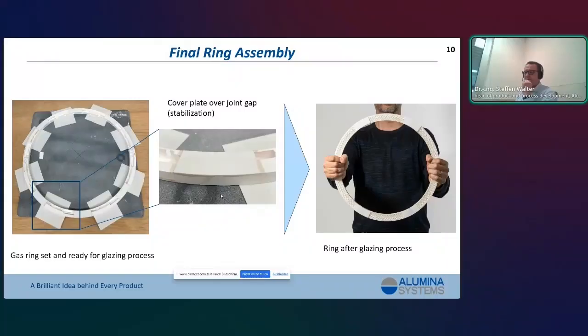So here we see the ring segments. They will now be assembled to one ring structure. They will be glazed with a special glass, and when this glass is applied onto the ring, it goes into the furnace in a second sintering step where the glass melts and fixes the parts to one ring structure. And here on the right hand, this is, I think, Norbert Gall, a colleague from Lithoz, who shows the ring after such a glazing process.